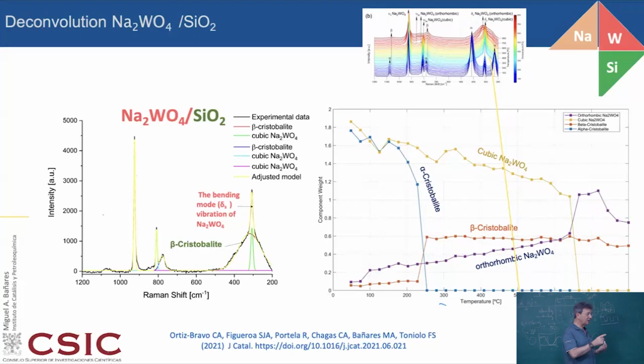And then with spectroscopy, you will observe things that are telling you which is more an active species, which is not. So this kind of, and I don't know if you will talk about SSITKA. Probably not, a little bit. So this is like one pulse, basically. You are flowing, everything gets a steady state, and then you switch and see what happens. Another way of doing things is the periodic modulation, where basically you do something periodic. You could make two isotopes also. You could make anything, because the perturbation can be anything. I told you, like, toluene, not toluene, okay. But the perturbation could be photocatalysis, and could be like light on, light off, light on, light off, light on, light off, and that will be also a modulation. Or you can be working with a system that you can quickly put high pressure, low pressure, high pressure, low pressure. You can do that, and you're doing a modulation.